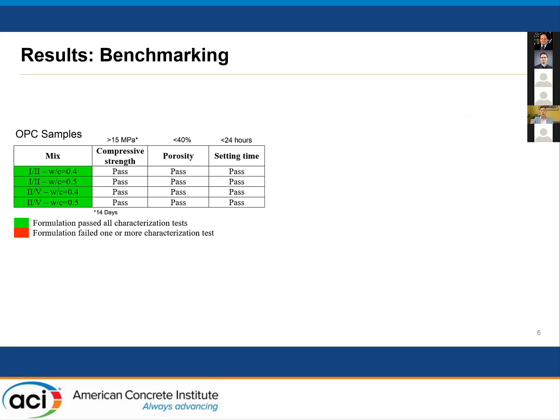So here I'm showing the results of our very first benchmarking effort, where we were looking at samples of Type I/II and Type II/V Portland cement for compressive strength, porosity, and setting time. Again, we were trying to benchmark these materials and ensure that we were achieving desirable properties like greater than 15 megapascal compressive strength, less than 40% porosity, and less than 24 hours of setting time. And of course, with all of these materials, they certainly passed our initial benchmarks for fresh and hardened state properties.